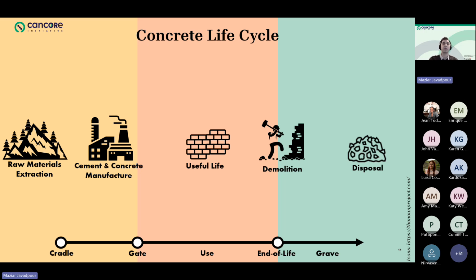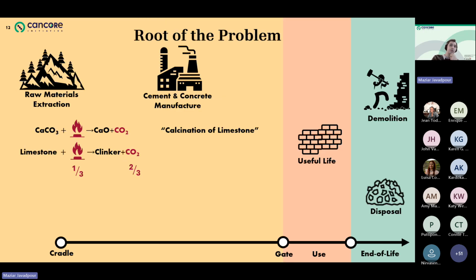The end of it is marked by demolition, where we have the disposal and the end of life of concrete. But the main part is the cradle to gate. This is where the root of the problem is, and as Sylvia put it, the calcination of limestone. Now, to break down when we make cement, we heat the calcium carbonate. This breaks it down to calcium oxide, or lime, plus CO2. This is about 1/3 of cement's emissions, and this is what fossil fuels is really getting us.